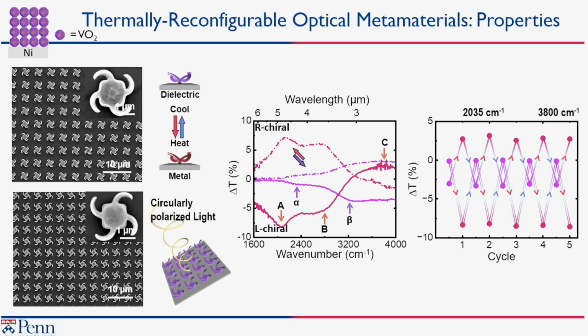So what you see is that the dashed dots versus solid lines are just the left and right-hand enantiomers. So again, you see this sort of mirror symmetry across the zero axis. But if you look at it in the insulating phase, you can see some photonic resonances here. But if you then heat it above about 75 degrees, above the phase transition temperature, they become metallic, and you see the idea that you now have plasmonic resonances in these structures.